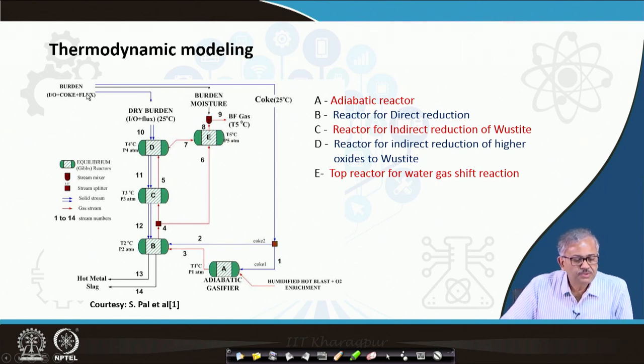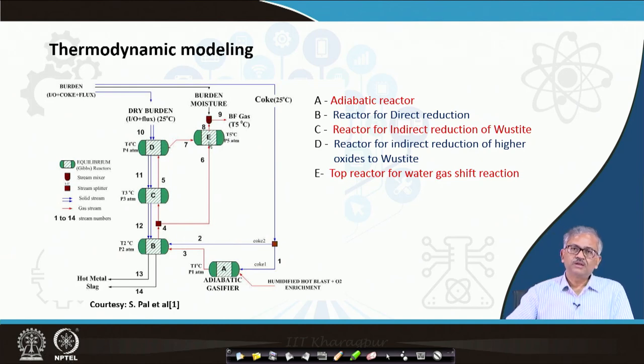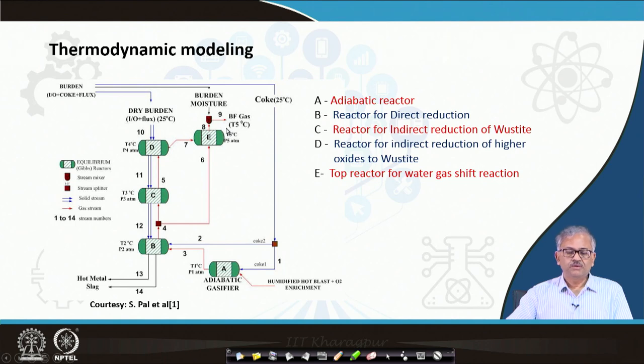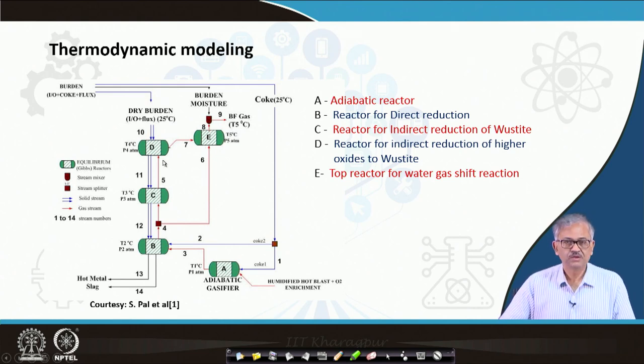From the burden, the moisture is taken out separately. The equilibrium CO/CO2 mixture from reactor D, the bypass CO, and the burden moisture are all mixed together and come to a thermodynamic equilibrium. This reactor is basically for the water gas shift reaction, where CO may react with moisture forming CO2 and H2. Finally, you will get the blast furnace exit gas composition and temperature from this calculation.